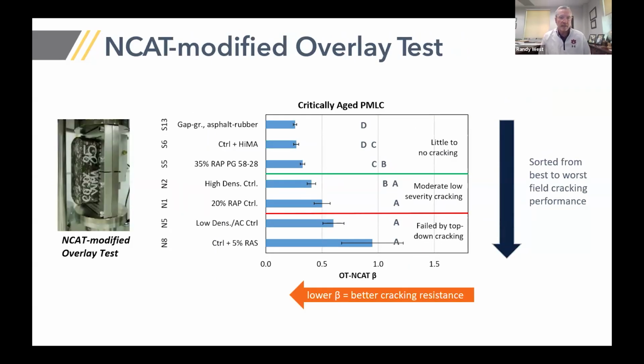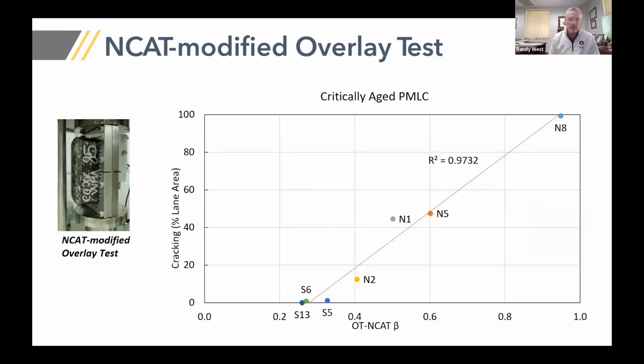We also did a modification of the overlay test based on some previous research that we had done at NCAT, using a smaller displacement and a faster cycling time. And we see also it did rank the mixes correctly, got good statistical groupings, and when we look at the correlation between the lab and the field, we see this very strong correlation, R squared of 0.97 here, a nice linear relationship. So this is a really good test for the correlation between lab and field.